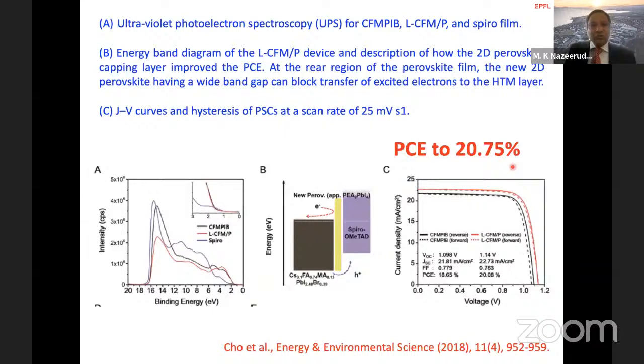Now, if you look at the UPS data, that's an energy level diagram. So this is our perovskite, the HOMO level and the LUMO level of the perovskite. And after measuring the UPS data, you can build the energy level scheme of the two-dimensional perovskite, which is shown here, this yellow line, and the spiro-OMeTAD hole-transporting material on the other side.